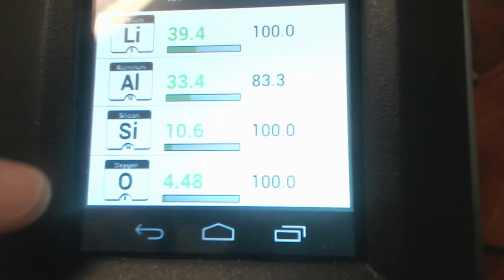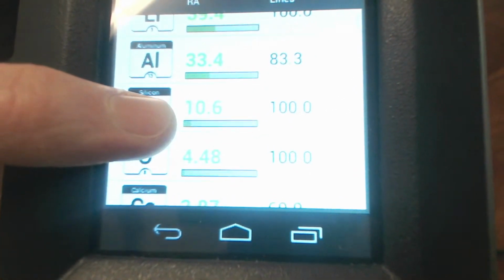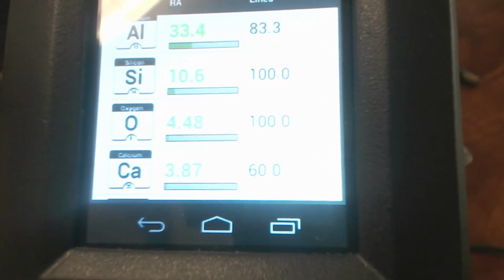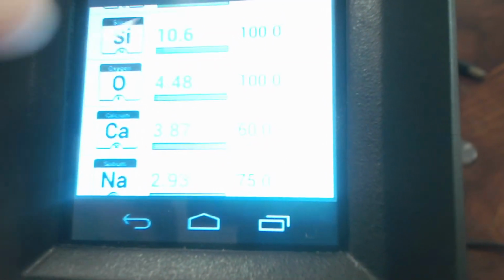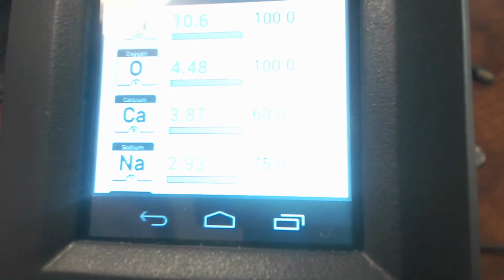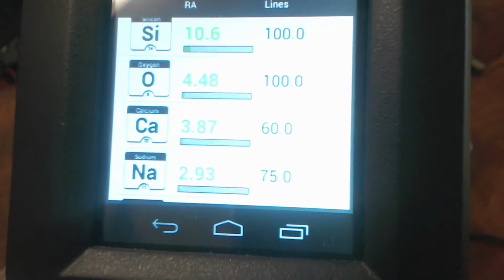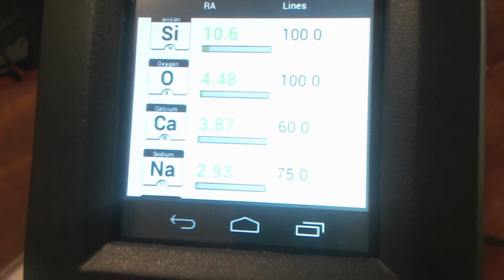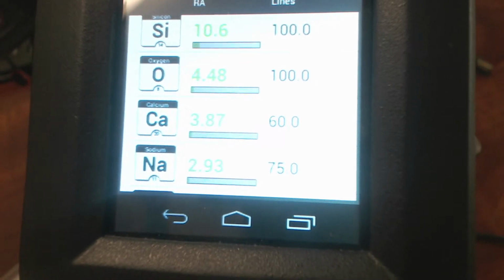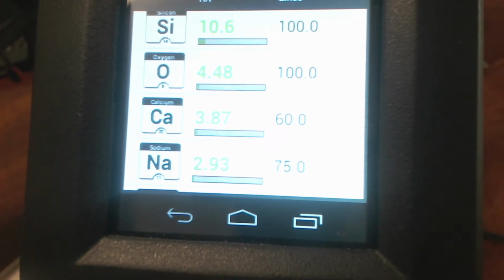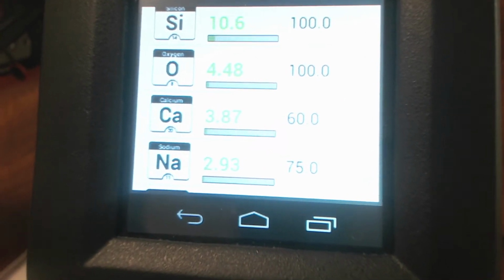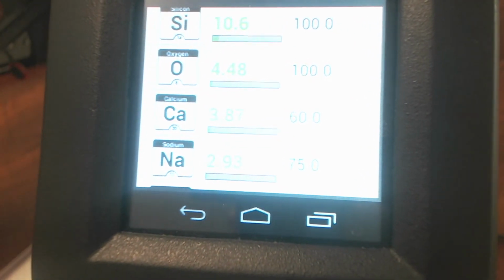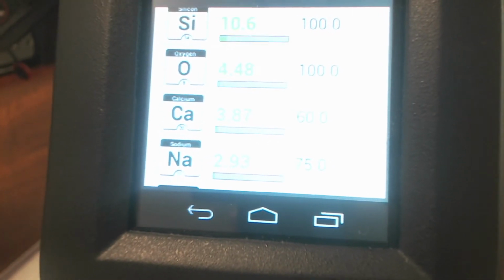Also notice that we've detected oxygen in this sample. So that's one of the cool things, one of the best things about LIBS. You can measure these light elements that you couldn't do before, like lithium, oxygen. We also see a fair amount of calcium and sodium in this result. And even though that may not be a part of the mineral makeup, those are common surface contaminants, and they're also super bright responders for LIBS. So we'll see calcium and sodium in almost anything, just because they're such a strong responder, and you find them in nature all over the place.